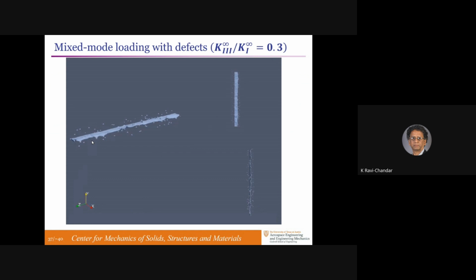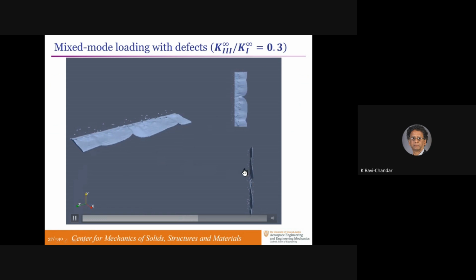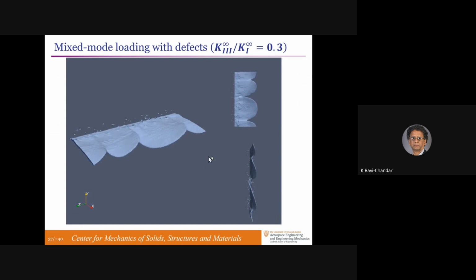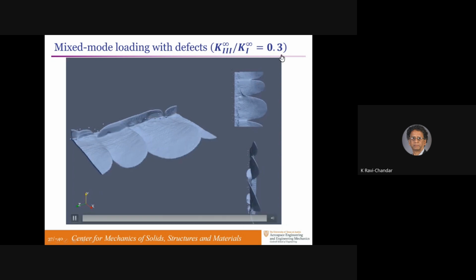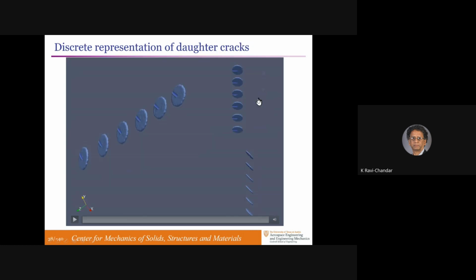Same idea, many defects in the field, and then they start perturbing the crack. When they get out of that, they've already formed a pattern of slanted cracks. The slant angle now is smaller. You can see the angles are smaller, and you can see they've established their slant depending on the ratio of K3 to K1. Again, they've run into the end of the simulation domain.